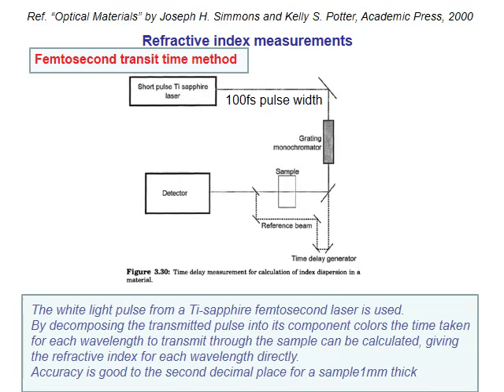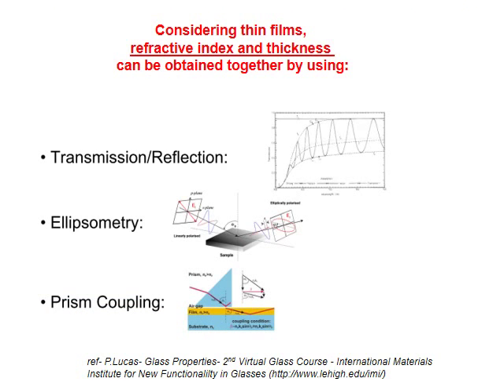A femtosecond laser can also be used to measure refractive index. The white light pulse from a titanium sapphire femtosecond laser is used. By decomposing the transmitted pulse into its component colors, the time taken for each wavelength to transmit through the sample can be calculated, giving the refractive index for each wavelength directly. Accuracy is good, to the second decimal place for a sample 1 mm thick. Considering thin films, refractive index and thickness can be obtained together by using transmission-reflection spectra, ellipsometry, or prism coupling.